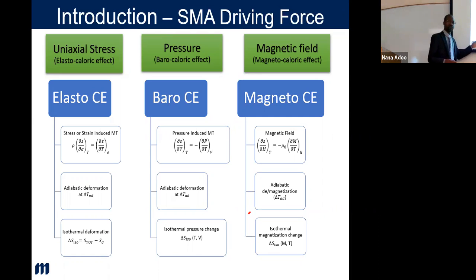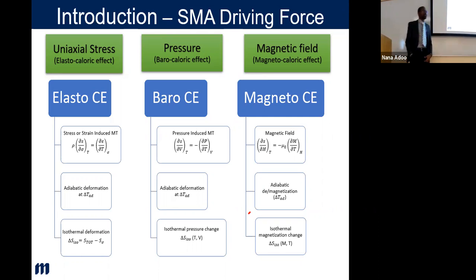In the isothermal phase, we try to relate the exactness to the thermodynamic functions, and try to quantify what's going on in there. So if it's stress, we know the entropy change there is related to a strain by temperature, which is the parameter we treat as constant, under constant stress as well, where the deformation takes place at a constant pressure. So we relate those to get the isothermal entropy change.